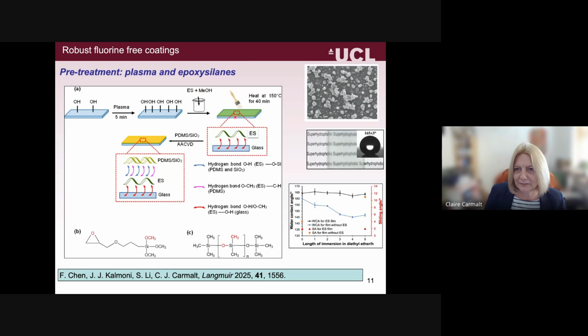And we were able to show that having this intermediate layer of the epoxy silane really helps with the robustness of the films. And this is just one example where we submerged them into different solvents. This one's diethyl ether. The top line is where we have the epoxy silane layer underneath our superhydrophobic film, and you can see over 5 hours there's not much change in the water contact angle, so they're still superhydrophobic. However, without the epoxy silane layer, you can see it dropping off from 0 to 5 hours, and that's because it's just not very well adhered to the substrate surface. So in the solvent, some of it's getting lost during the submersion.